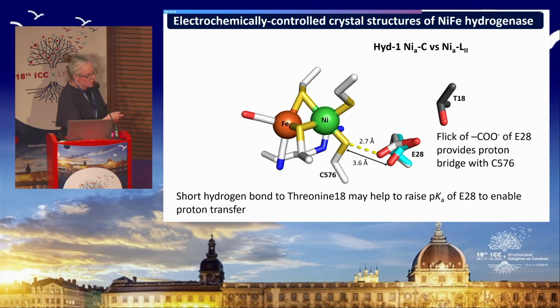And I just show these structures overlaid here. This is the structure of the nickel C state overlaid on the nickel L2 state. And you can see that the way that that glutamate flick has brought it from being 3.6 angstroms to 2.7 angstroms from the active site. And it's absolutely conserved in this position in all of the other states, and just in this nickel L2 state it comes within hydrogen bonding distance here.